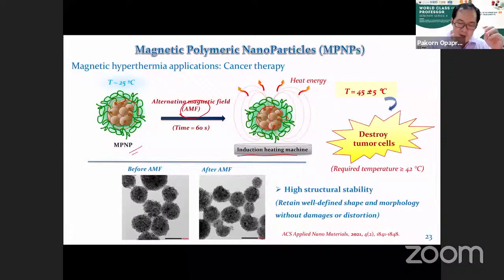In only about 1 minute, 60 seconds, we can heat the particle to around 45 degrees Celsius. And this is higher than the temperature used to destroy tumor cells. So as a result, the material has very high potential for magnetic hyperthermia application, especially in cancer therapy. And after heating to this temperature, the structure is still intact, so they have high shape stability.